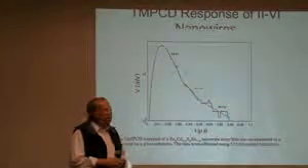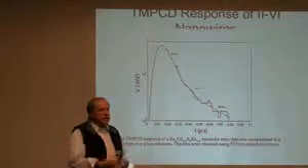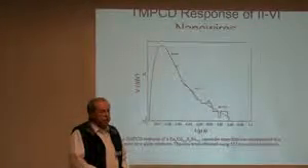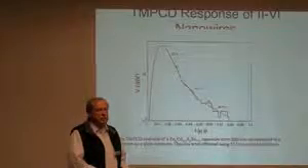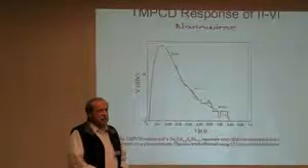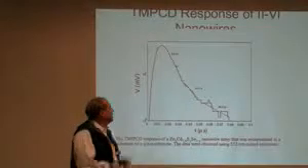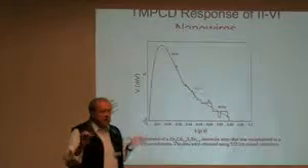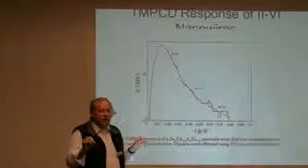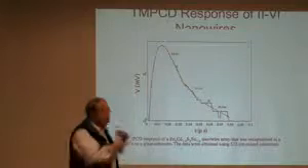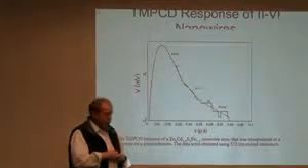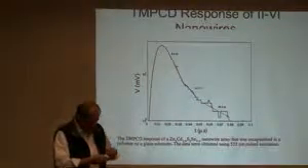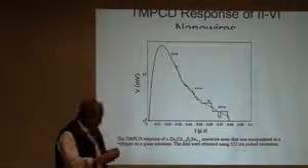These materials are quite easy to make compared to the tandem structures that are used in the high efficiency space photovoltaic technology. Those are quite complex and difficult and expensive to grow, whereas the nanowires will grow without strain because they're wires. They'll grow out of a substrate, and you can obtain this composition variation along the length of the wire. So this has some possibilities for future generation photovoltaics.